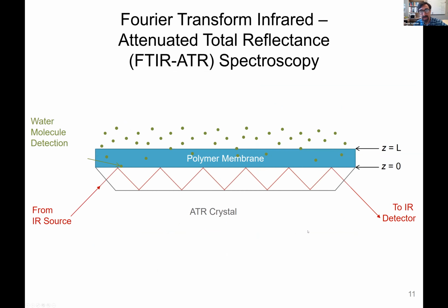So in order to measure transport, one of the techniques we really like to do in my lab, because we can separately and directly in the same measurement measure absorption and diffusion, which for absorption diffusion based transport through membranes, the product of those two is the permeability. And so if you did a membrane permeation measurement, you get permeability, but we can get these two rather accurately and separately: solubility and diffusivity.